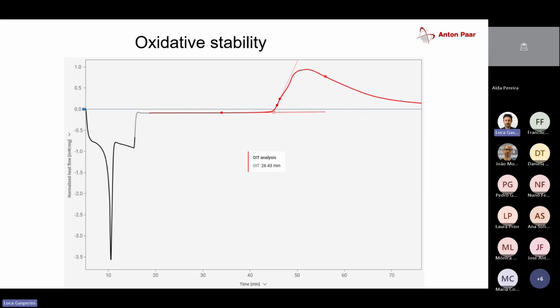However, putting the pigment into the material, I might have changed its structural properties, or they were not good enough from the very beginning. So I put a filler in, like calcium carbonate, which we have also seen. Then I run my oxidative stability measurement, OIT, again, and I receive a much lower value, like 18 minutes, and that's not even sufficient for the material to be used. So I put stabilizer into the system, and then I run my OIT analysis again, and then my value increases to 30 minutes. And then I might say, okay, this is good enough oxidative stability, and the final processed product can actually go to the market and I can actually sell it. So the OIT measurement is actually a nice tool to see how various components that I add to my matrix can affect the stability of the sample.